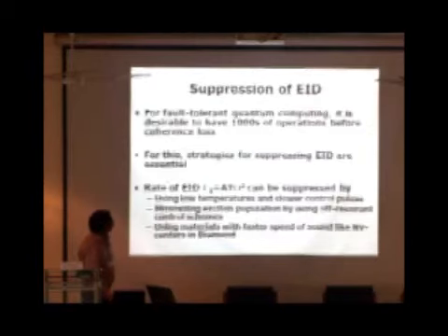For future direction, how do we suppress EID, the dephasing? One thing is you can use low temperatures and slower control pulses. You can minimize exciton population by using off resonant control schemes, and you can use materials with faster speed of sound like NV centers in diamond to have longer dephasing times.